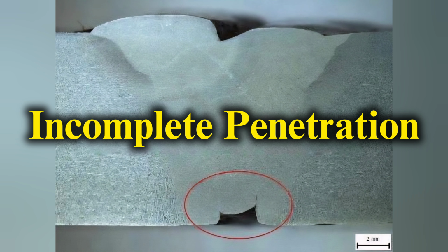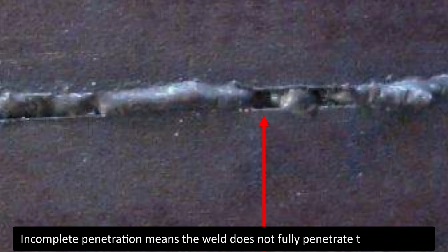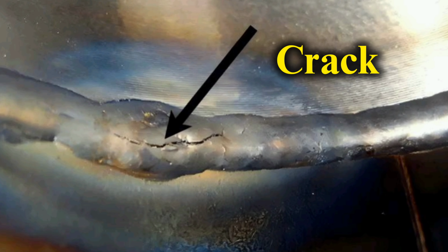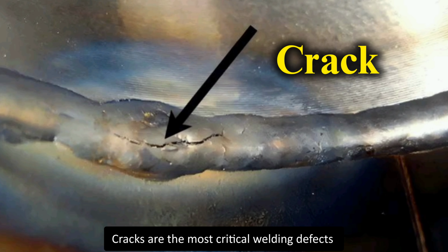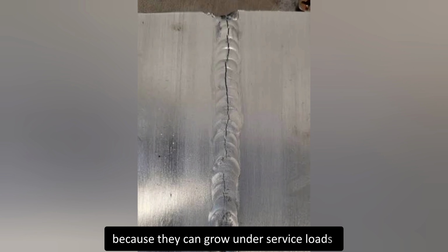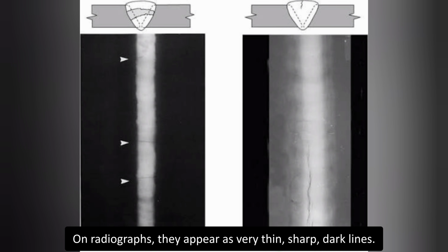4. Incomplete penetration. Incomplete penetration means the weld does not fully penetrate the joint root. In radiography, it appears as a straight dark line at the center of the weld. 5. Crack. Cracks are the most critical welding defects because they can grow under service loads. On radiographs, they appear as very thin, sharp, dark lines.